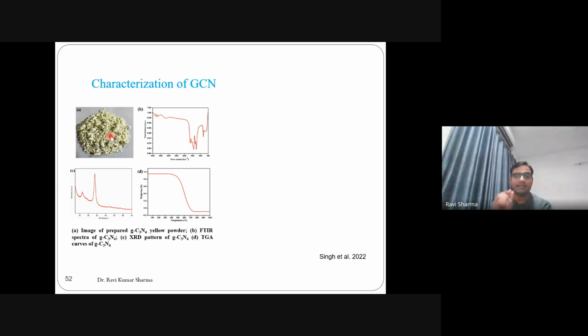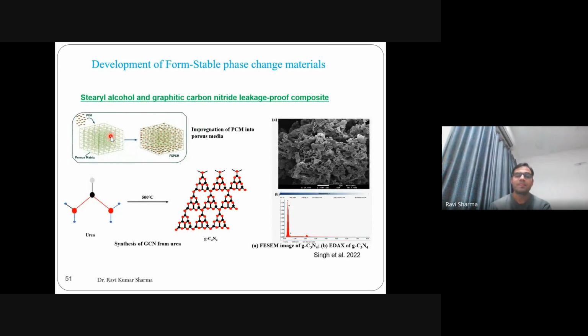The chemical name for this is graphitic carbon nitride. So we burned the urea at 500 degrees centigrade and it was converted into graphitic carbon nitride, with the chemical representation g-C3N4. This is the FESEM image of graphitic carbon nitride, and you can easily see the pores here.